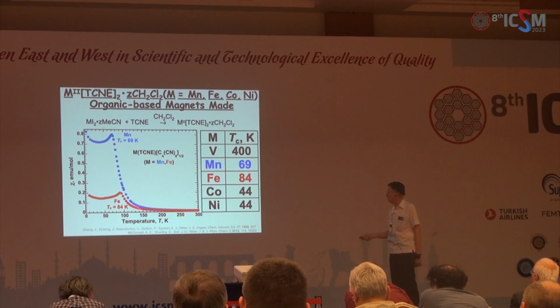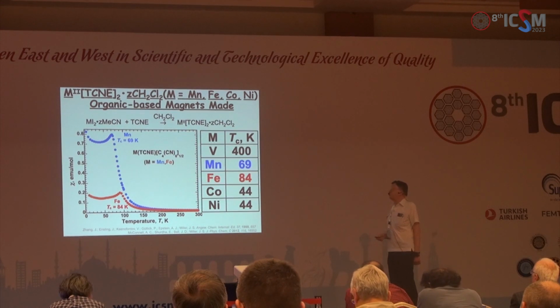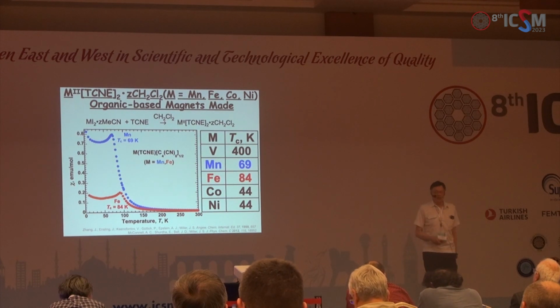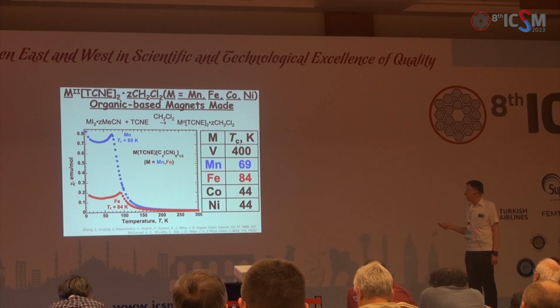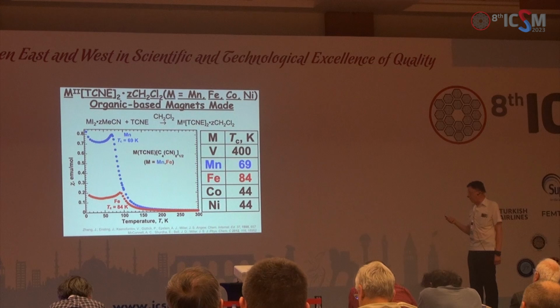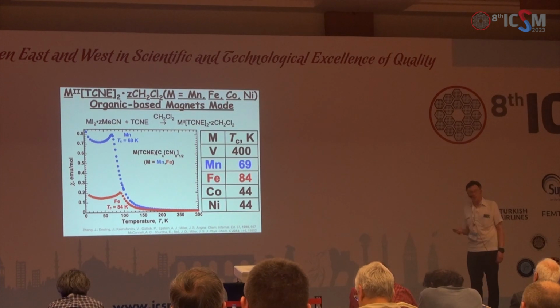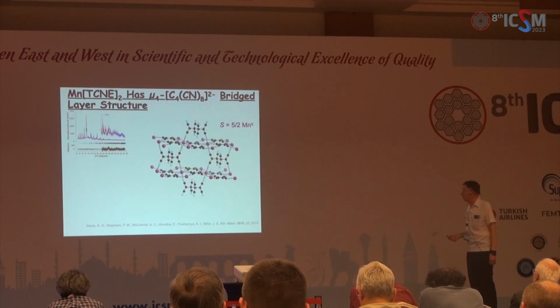If you look at chi versus T, there's a little glitch suggesting an anti-ferromagnetic coupling, but it does order, as we'll point out, to 69 Kelvin, nowhere near 400 Kelvin. But nonetheless, it's still a respectable value.